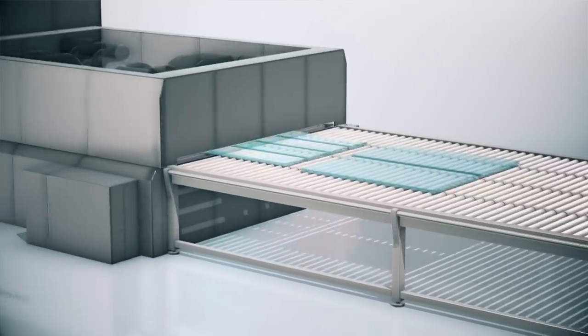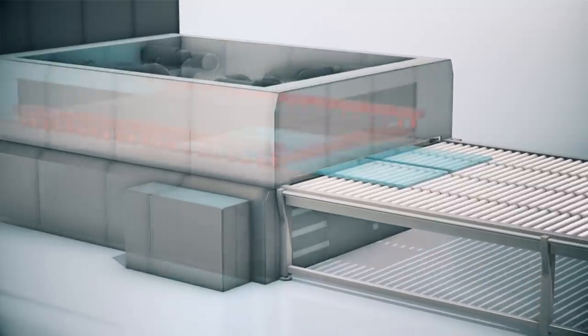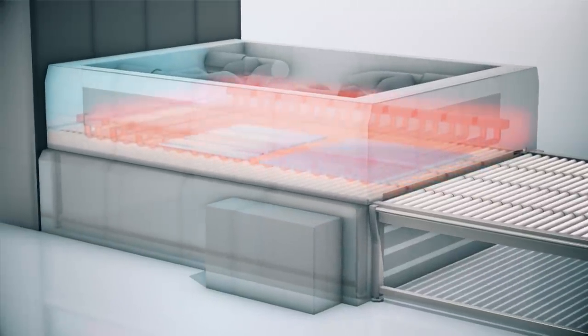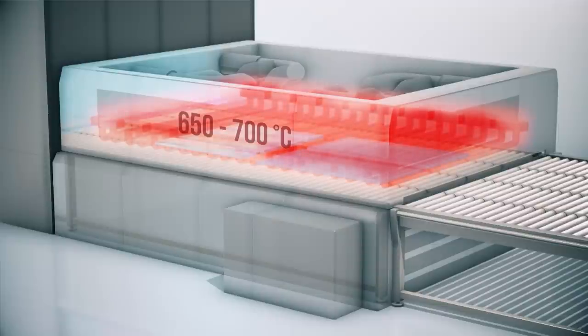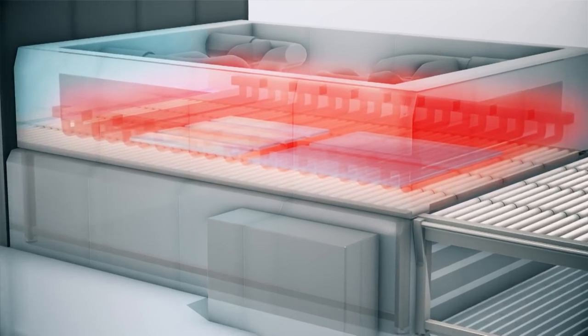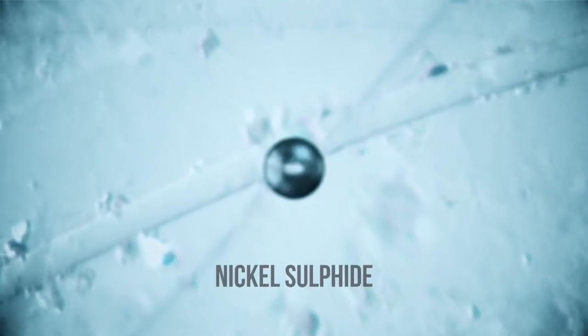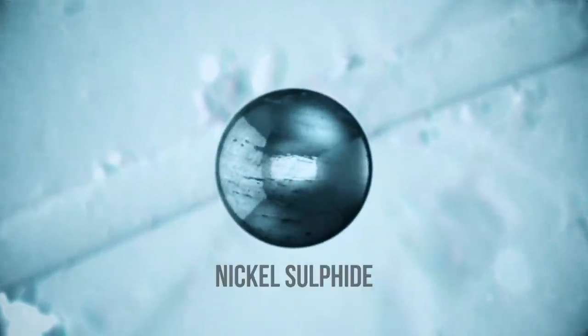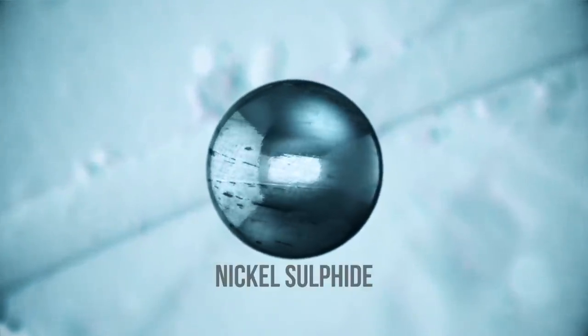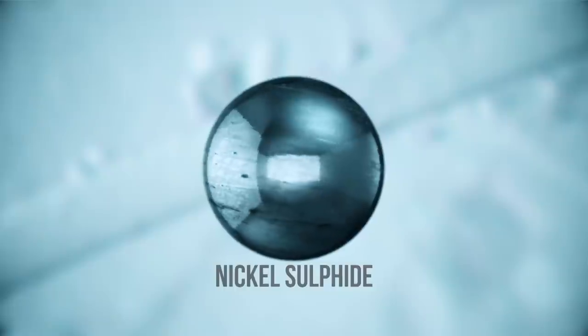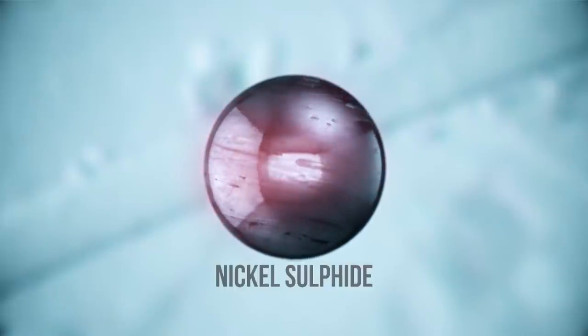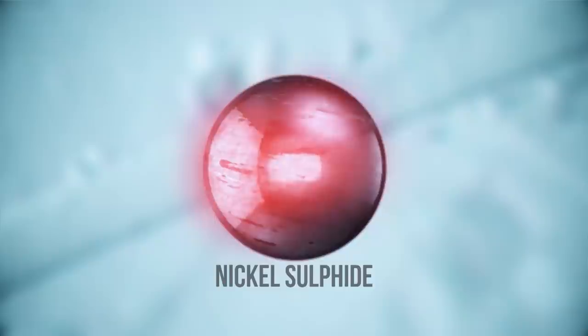This is how tempered glass is made. Normal glass is put into a furnace, which is heated between 650 and 700 degrees Celsius to soften it. This is the first step to making the glass tougher. If there is nickel sulfide present, you can't see it with the naked eye, because it is even smaller than a grain of salt. But here's the thing, it's not just the glass that is heated. Nickel sulfide too heats up, and this causes it to contract.